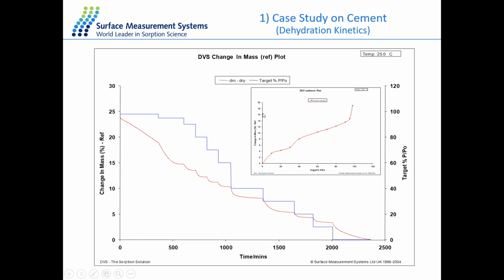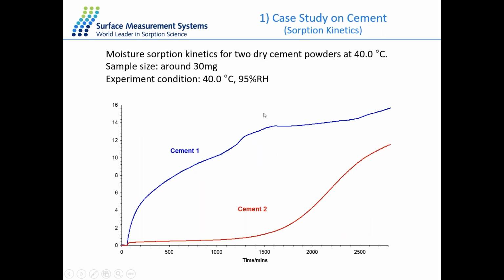And the next study on cement sample, this time we studied the sorption kinetics. So here we have two different kinds of dry cement powder, and then we expose them to 95% RH at 40 degrees for 2 days. And here is the change of the mass plot. So the cement 1 sample, which is the blue line here, has a very rapid increase at the very beginning, and then a gradual increase over time.